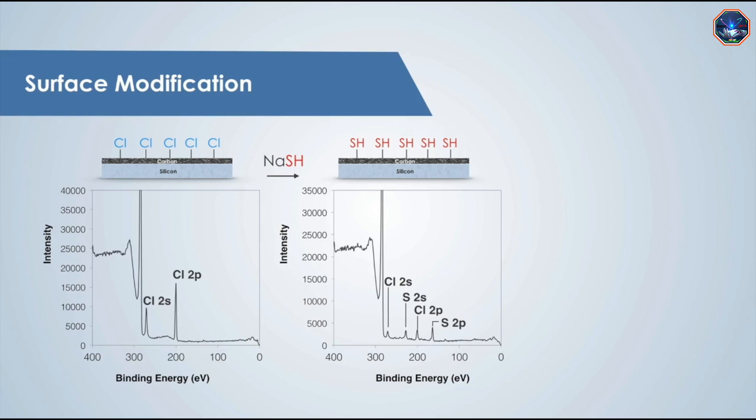The picture at the top is what we hoped the surface would look like after this reaction, but it looks like the reaction was not complete. A more accurate picture would look something like this, where most but not all of the chlorine has been replaced with sulfur.